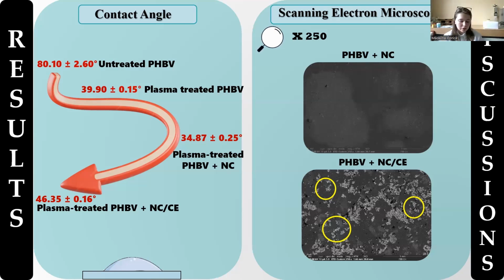The addition of the nanocellulose leads to a decrease of around 5 degrees, while the presence of curcumin in the last sample raises the contact angle by around 6 degrees as compared to the plasma-treated PHBV. The SEM images presented correspond to the PHBV and the nanocellulose sample, and the other below, where the curcumin is also present in the nanocellulosic mixture. The PHBV and nanocellulose sample exhibits a uniform covering, while the sample below is unevenly distributed due to the presence of curcumin in small groups throughout the surface of the film.